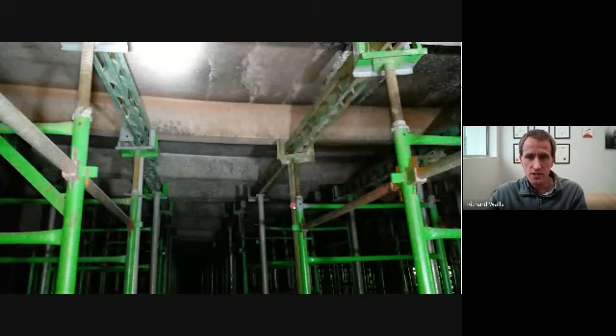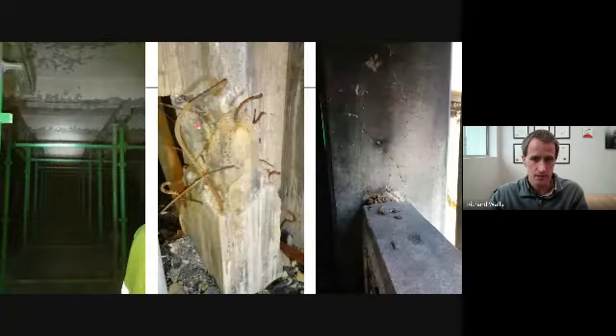So now this is what a concrete structure though looks like when it's been severely fire affected. I actually need to go back to the structure next week. Very large scale damage. This was the CFD model I showed you earlier. And the fire spread, you've got very severe structural damage, large scale cracking, spalling. This is turned pinkish. Pinkish tells you it's around 600 degrees Celsius in that vicinity. Buff color, so this fire spread affected this, permanent deformations. Chances are much of this would have to be demolished.